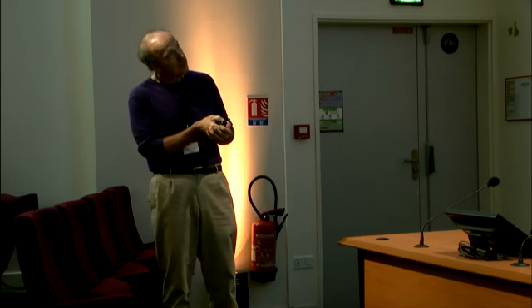You can see there's a shift to more negative potentials here, indicating that this nanoparticle is not as good a catalyst as bulk platinum. And then as he gets smaller and smaller, you can see further and further shift, and this is published data and has been quantitatively interpreted. And so it gets worse and worse as the particles get smaller. And then finally, something really interesting happens when we get down to 100 atoms. There's actually a shift in the mass transfer limited current. And we're not sure what this is due to yet. We're actively studying this.